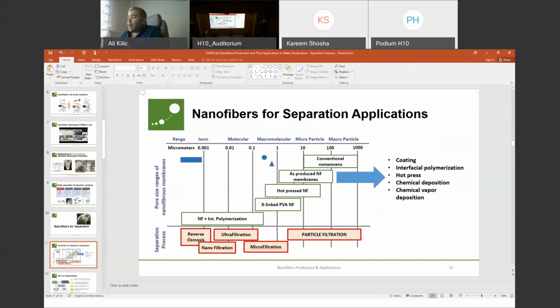Due to that reason, we are making some modifications on these nanofibers. If we press on them and make them more like a porous membrane structure, hot pressing is one method. We can use some cross-linking techniques. And also, at the end of the day, the best performance we were able to obtain is using the nanofiber layers as mid layers. They are fibrous mid layers. They have high tortuosity. So due to that reason, the use of nanofibers in our membranes gives us the opportunity to go for high water permeability. For that reason, generally interfacial polymerization is utilized.